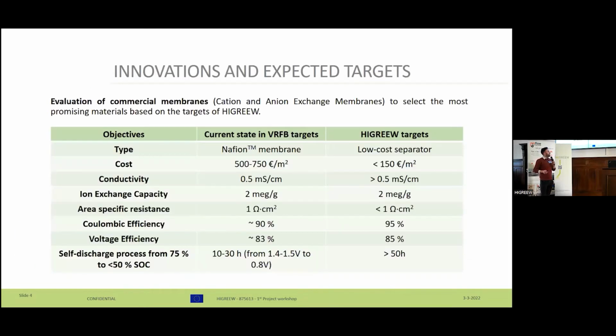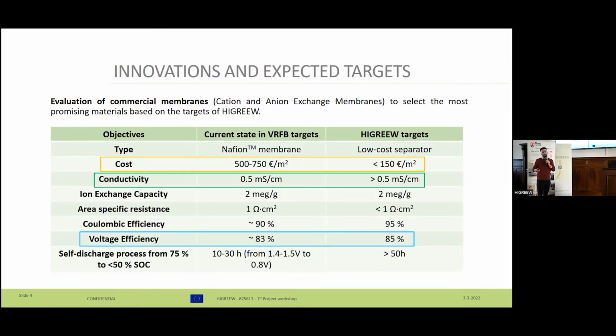The targets of the HIGREEW project were considered taking into account the state of the art in vanadium redox flow batteries, and in concrete the Nafion type membranes, which is the most used. And here in this slide, if you can see the values of this table, they are quite optimistic, but I must say that some of them are of relevance, such as the cost, the conductivity, and the voltage efficiency, which is related to the cross-mixing of the active species, related to the voltage efficiency losses. So we have made a kind of screening selection of different commercial membranes based on cost, conductivity, and permeability tests.